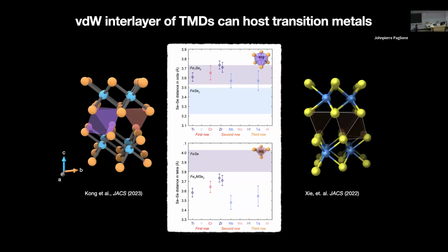And over here, what I'm showing on the left and on the right are the 1T and 2H structures of the TMD, right? So in both cases, you can have octahedral and tetrahedral sites. By far the most common intercalation compounds of TMDs have this 2H structure. There are a few based on this 1T structure for the zirconium and hafnium dichalcogenides. And by and large, when you intercalate transition metal ions, or when you grow crystals that have transition metal ions intercalated, more on that point later, in these materials, they will sit in the octahedral sites in pretty much all cases, with the exception of some of these 1T system TMDs, where you can get a mixture of the octahedral and tetrahedral occupancies. And in part, that can be understood simply by looking at the geometry, the size of those octahedral and tetrahedral sites.